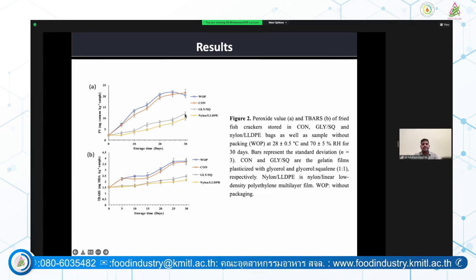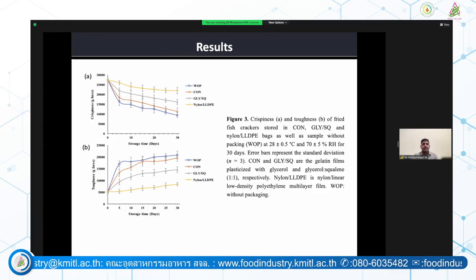And we can see the second most with the huge difference from that of control was squalene incorporated bag samples, and next is the nylon commercial bags. So these results were interesting to indicate that the storage stability was good, and these squalene incorporated bags can be good for the oxidative stability.